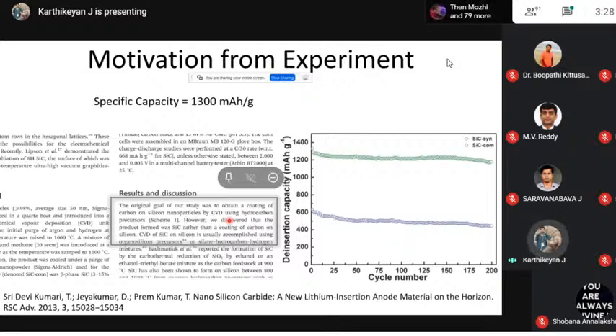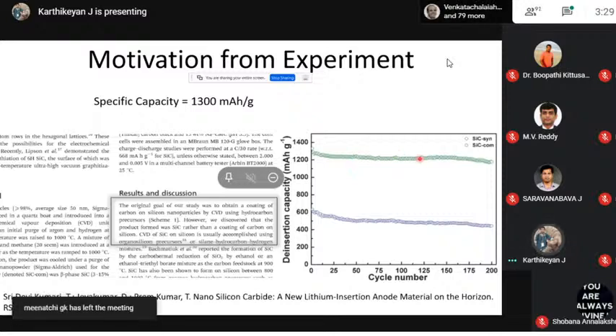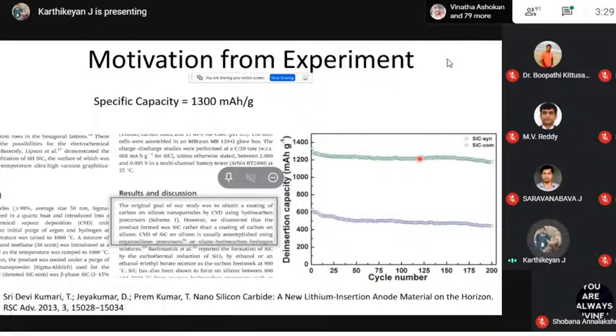Then the charge discharge cycle was giving very, very low capacity compared to silicon, but the capacity was retained even after 200 cycles, right? It is not really expected from a silicon nanoparticle. For a silicon nanoparticle, we expect more capacity, but the capacity should fade when you go for more and more cycles. But later they understood that they had really formed silicon carbide nanoparticles, and they published this result.